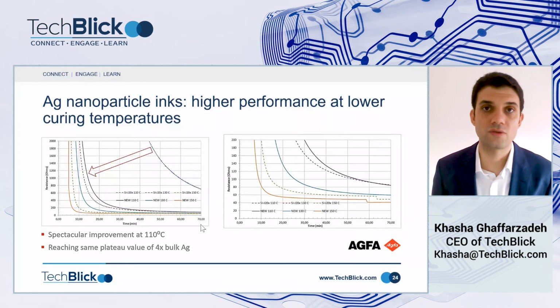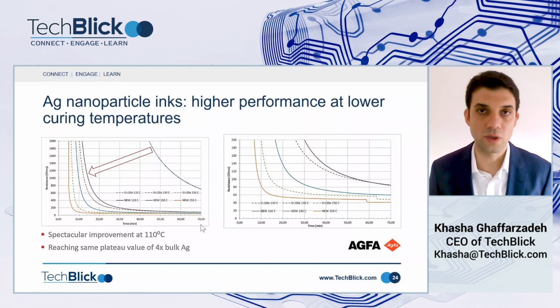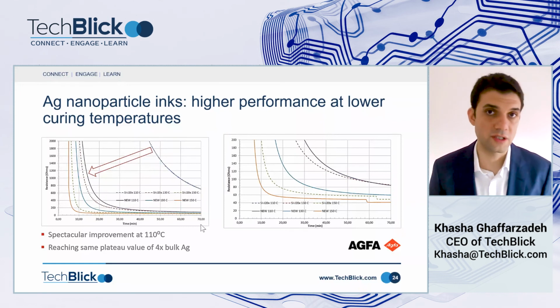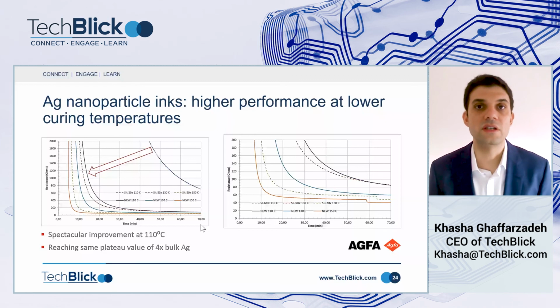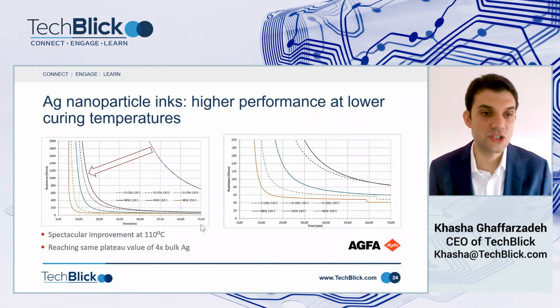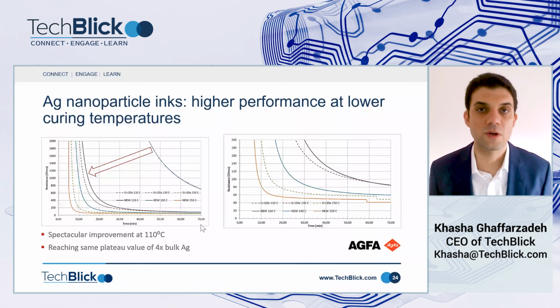Agfa actually also acquired recently the assets of Clarion, so now they have solvent and water-based silver nanoparticle inks in their portfolio. The two charts in this example show you the same thing. One of them is zoomed in and the other one is zoomed out. It shows you that for a given curing temperature, the achieved conductivity has dramatically improved. So in particular, look at the case when the curing is just 110 degrees Celsius. You can see that the latest generation of inks are achieving much better conductivity, much lower level of resistivity.